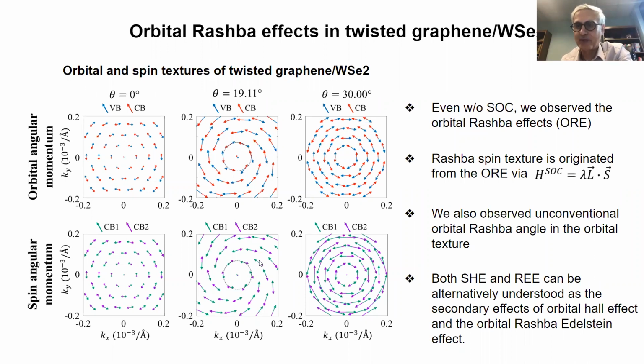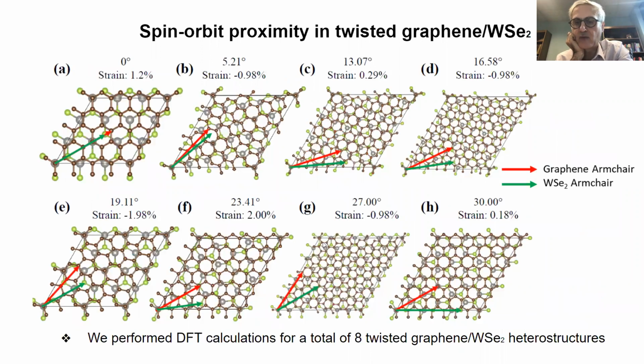Okay, one more question. When you select a unit cell with strain to make it commensurate, do you think in reality the system will be strained in order to lock into a large Moiré lattice, or is it energetically favorable to do so? What does this look like? That's right. That's a very good question. My honest answer is that probably not.